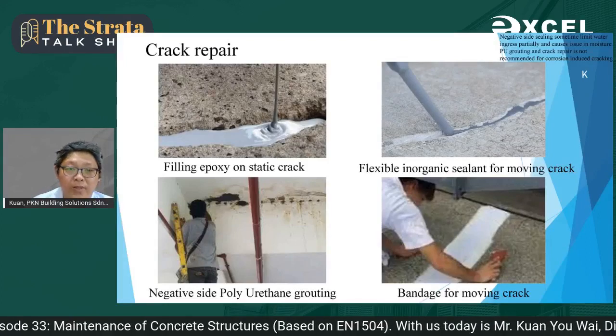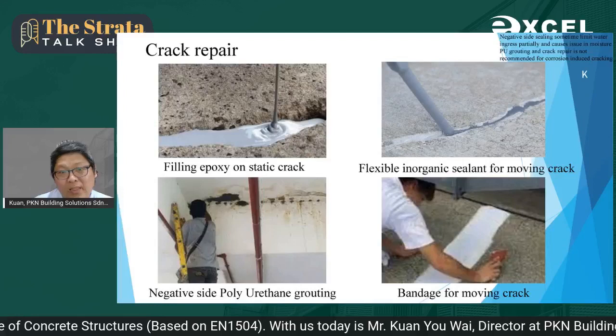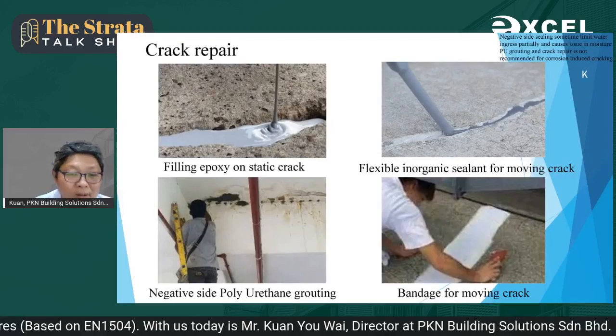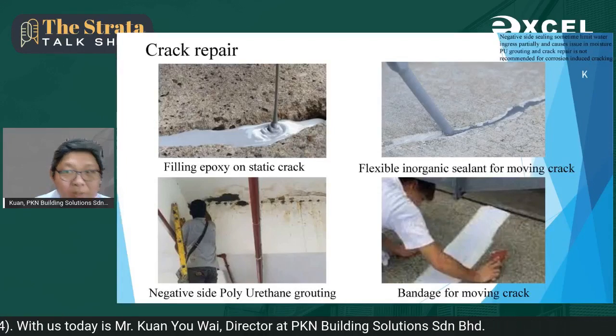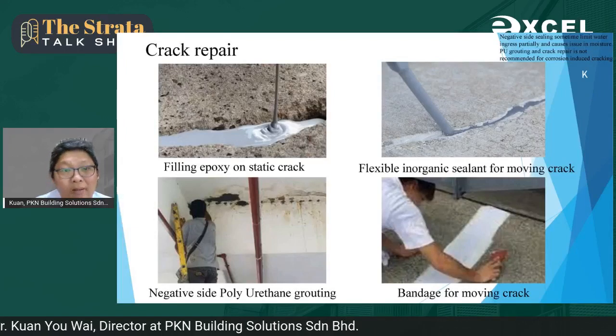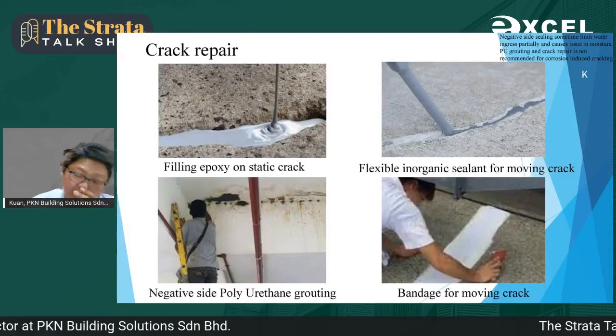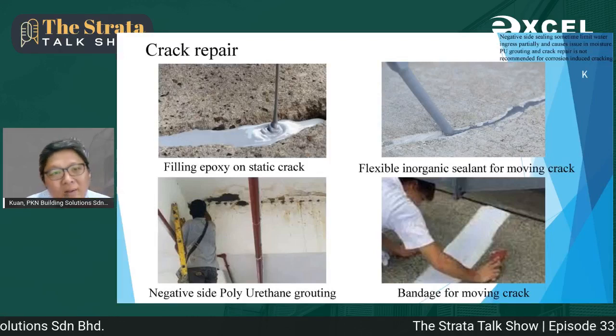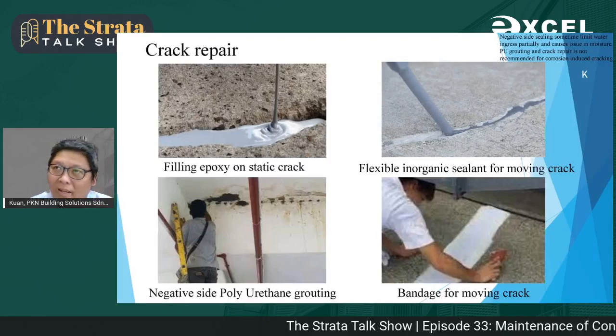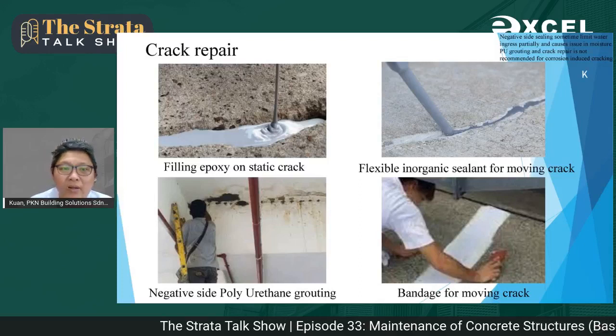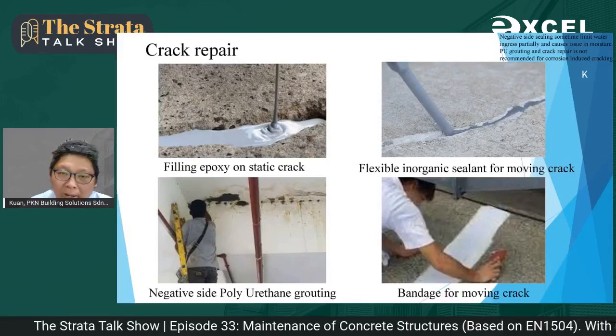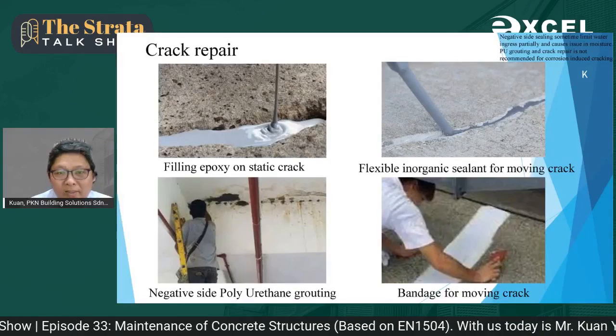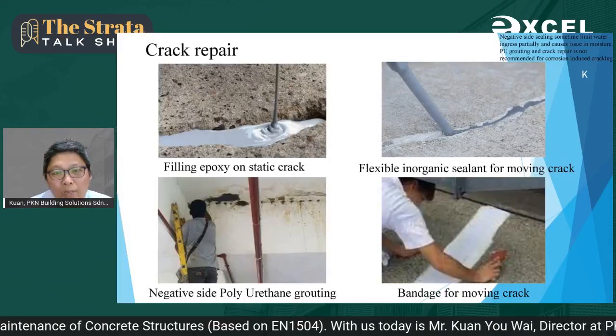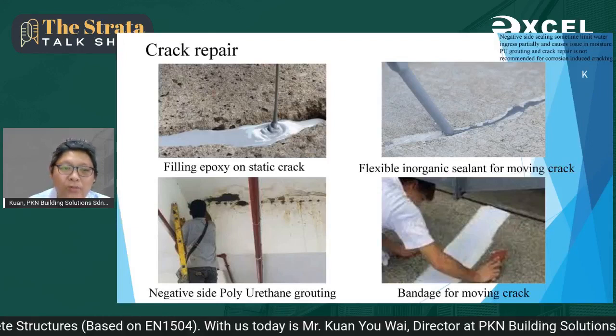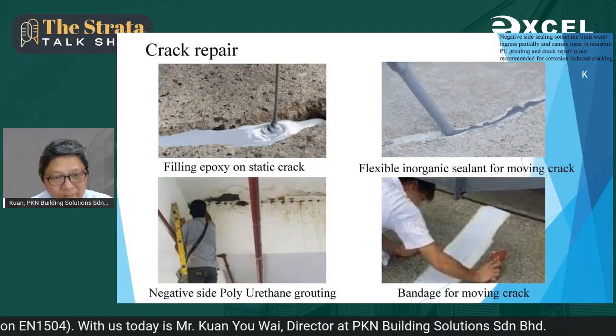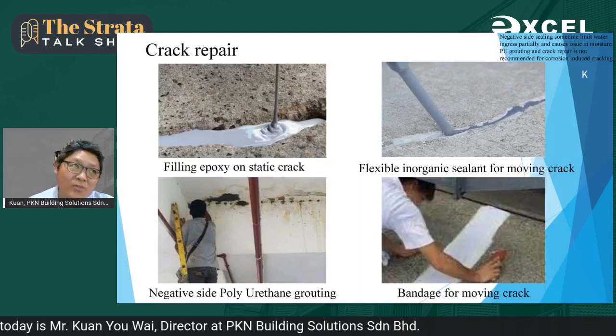So one of the ways is to fill the crack with epoxy, on the condition the crack is the static type of crack, maybe due to natural shrinkage. Okay, then epoxy can be considered, but epoxy is not heat and ultraviolet stable, so it cannot be done on an area that is exposed to the weather. For any type of dynamic crack, flexible sealant is actually more workable and more effective. PU grouting, I personally don't recommend unless it is caused by natural shrinkage.